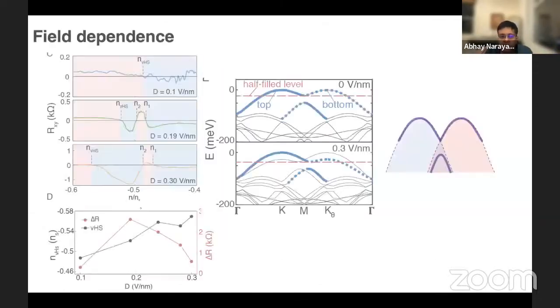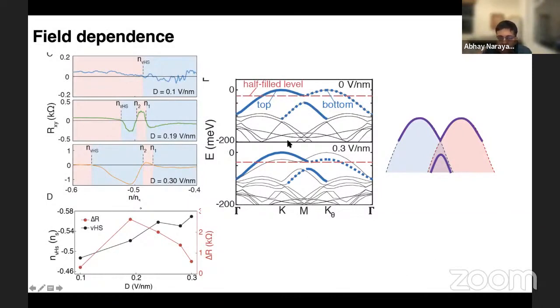Now you can ask, why does it show this kind of behavior? And we can gain some insight into this from what the electronic structure does as a function of this electric field that you apply. Now, remember that if I have a bilayer system and I apply an electric field perpendicular to the layers, then I have a difference in the potential energy for electrons in one layer versus the other layer, just integral of E dot dl. And so when you start to apply this electric field, the valence bands on each of these layers, which were originally degenerate, are now going to be displaced relative to each other.